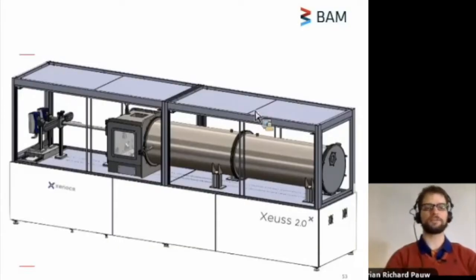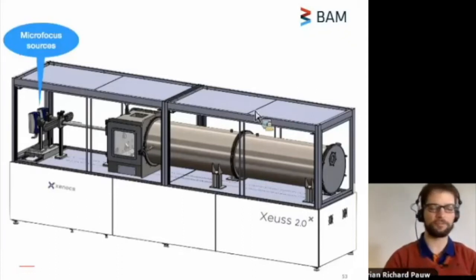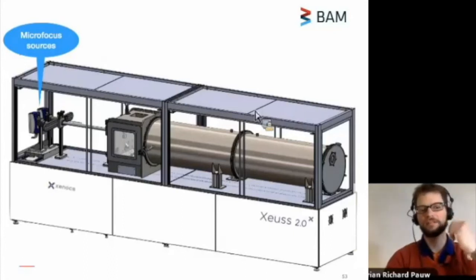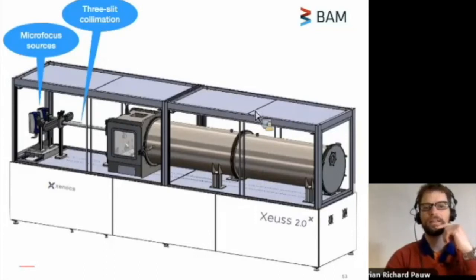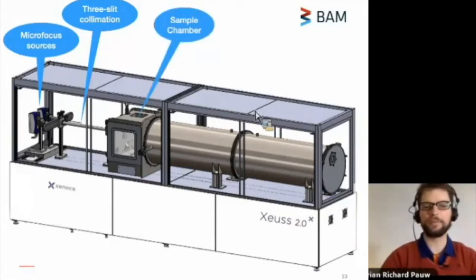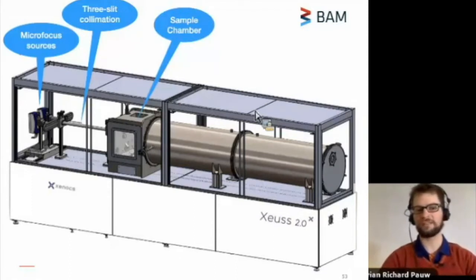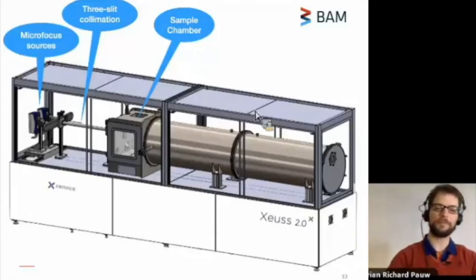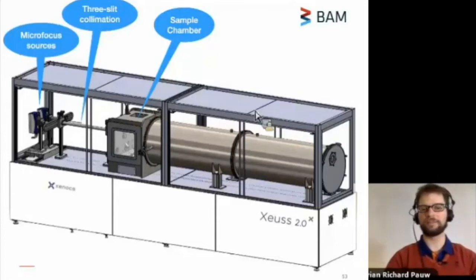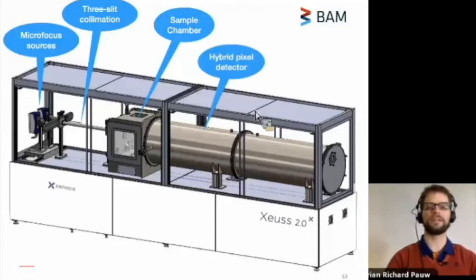But if you look at the instruments, you actually recognize many of those elements from the schematical description. So we have our X-ray sources over here. In our instrument, we have two X-ray sources, slightly different energies. I will explain why later. We then send these X-rays through a collimation system, which in our case consists of three sets of scatterless slits. It then enters our vacuum sample chamber. This is a very large chamber for instruments of this type. We have 50 by 50 by 60 centimeters of space in there, enough space for very large experimental setups, so we can do in situ experiments. And after that, it hits the hybrid pixel detector, which sits inside this big vacuum tank on a motorized stage.